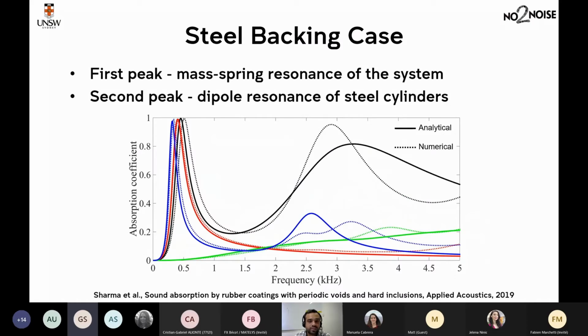This is with steel backing, for those four different coating designs. So when you have a steel backing and when you have voids, you always have this mass spring resonance, this peak of really high sound absorption at low frequency, right? This is for when you have two voids in the direction of sound propagation.